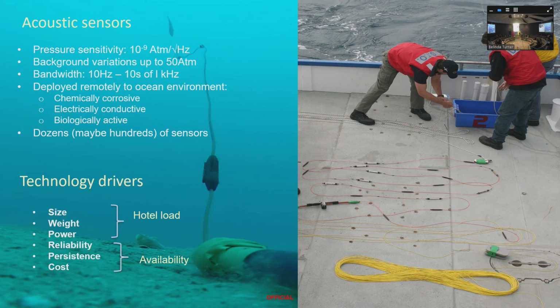That's a very difficult challenge, and you need to do that over from about 10 hertz up to tens of kilohertz. So it's quite demanding. You need to go down to quite low frequencies because that's where the sound propagates the furthest underwater. And you need to be able to do this in an environment which is chemically corrosive, electrically conductive, and biologically active.